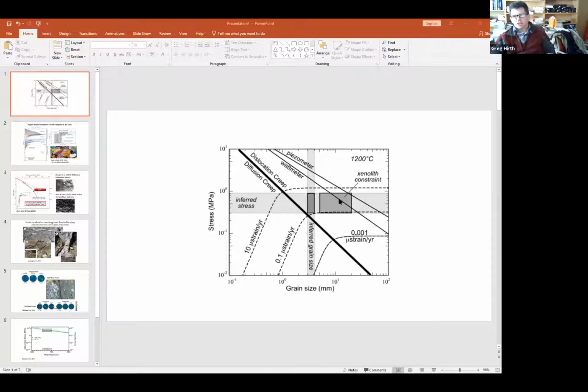So to me then, that was really, really cool, but it also made me ask a question of, okay, to make it work though, you still needed to have a transient viscosity that was much lower than the steady state viscosity, which is something that is likely for dislocation creep rheology.